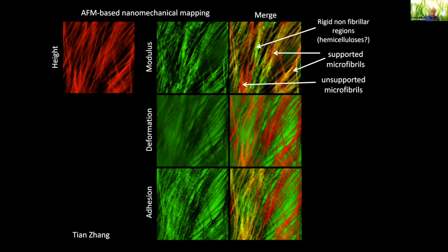So this is not cellulose here, but it's some matrix component that evidently is fairly stiff. We can see regions with high adhesion. So we think of these as pectins. Pectins form the matrix. Pectins are acidic polysaccharides in the cell wall, and they're the same things that cause a gelling of pies, for example, or jellies.